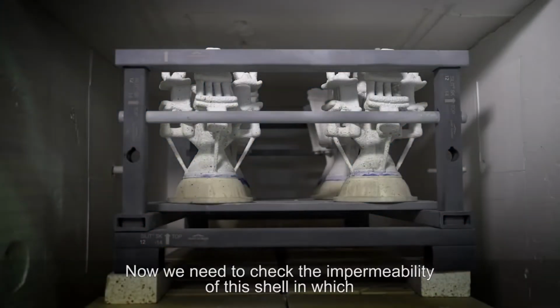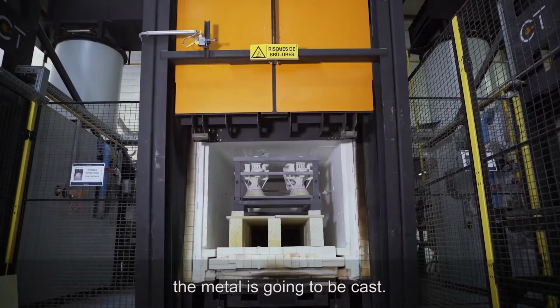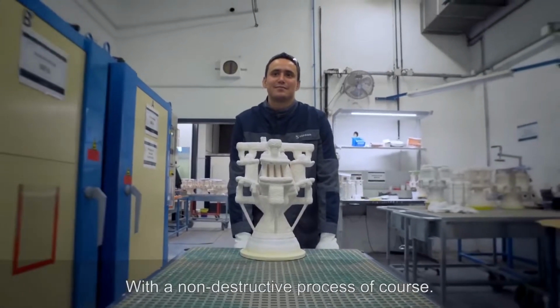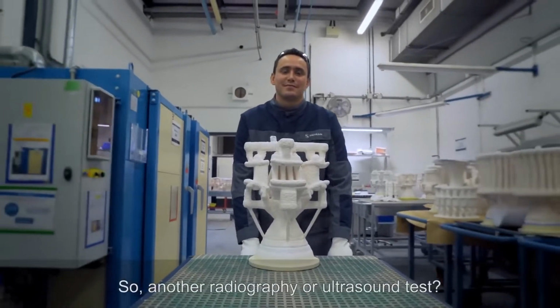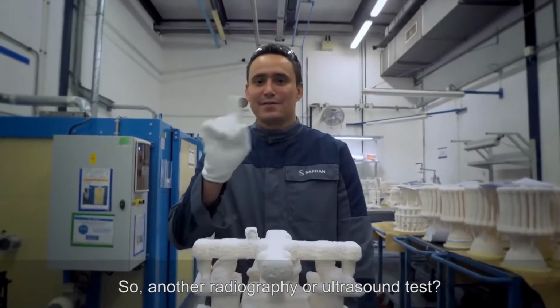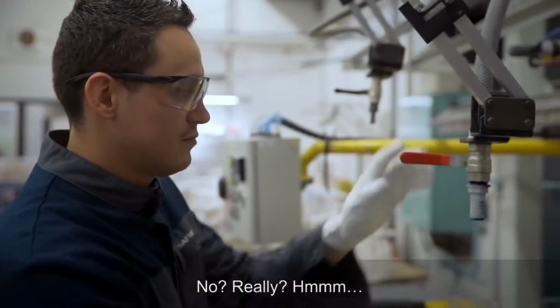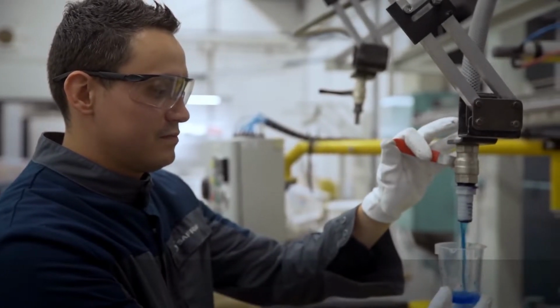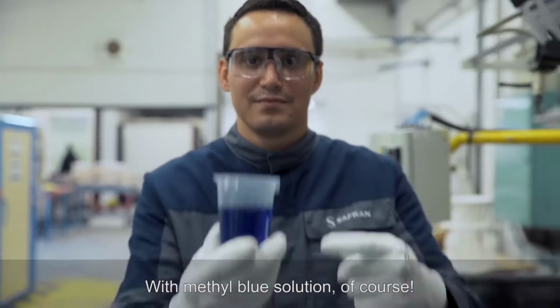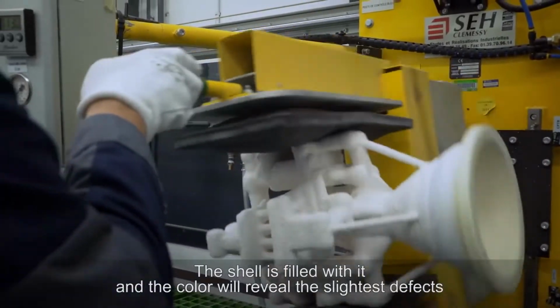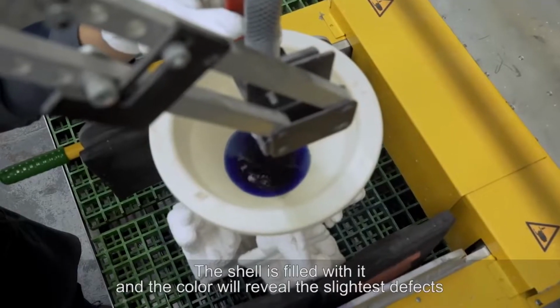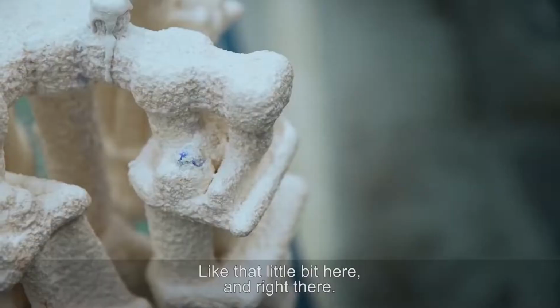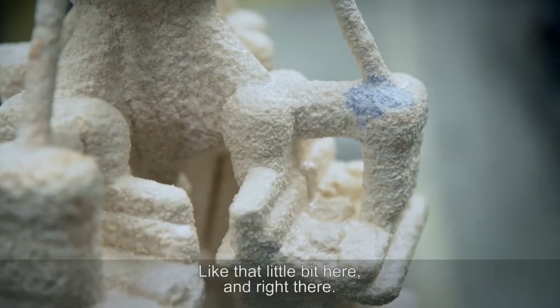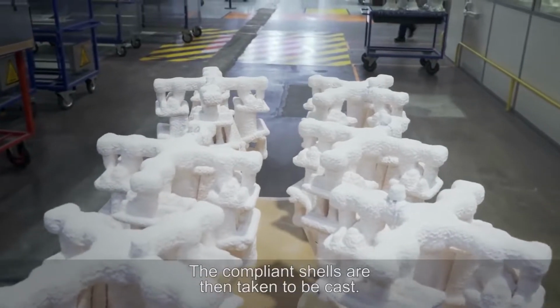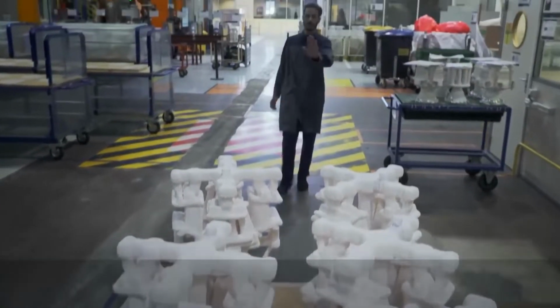Now we need to check the impermeability of the shell in which the metal is going to be cast with a non-destructive process, of course. So another radiography or ultrasound test? No? Really? With methylene blue solution, of course. The shell is filled with it, and the color will reveal the slightest defects by making them turn blue, like that little bit here, and right there. The compliant shells are then taken to be cast.